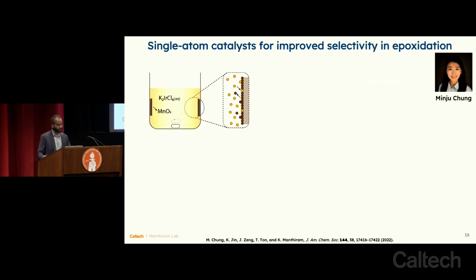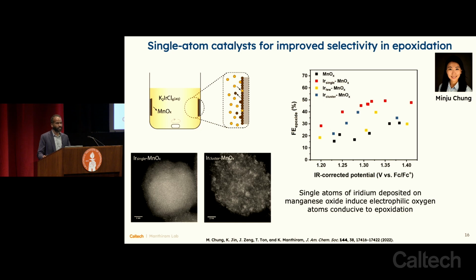We've then continued to develop new generations of catalysts. Here I'm showing that you can decorate the manganese oxide with iridium single atoms. These iridium single atoms make a local environment on the catalyst that is even more favorable for epoxidation, so that we can take what was 30% for a Faraday efficiency on manganese oxide and make that 50% instead with an iridium decorated catalyst. And now in our lab, in unpublished results, we've gotten up to 80%. So we're continuing to make this a more and more selective process, one which is actually being noticed now by industry, and we're hoping that we'll be able to actually spin this out into something that could help drive decarbonization of epoxide synthesis.